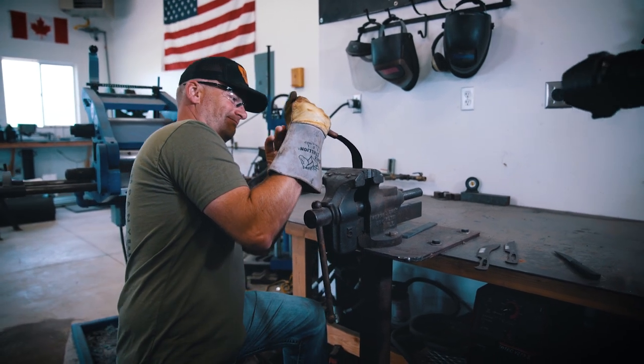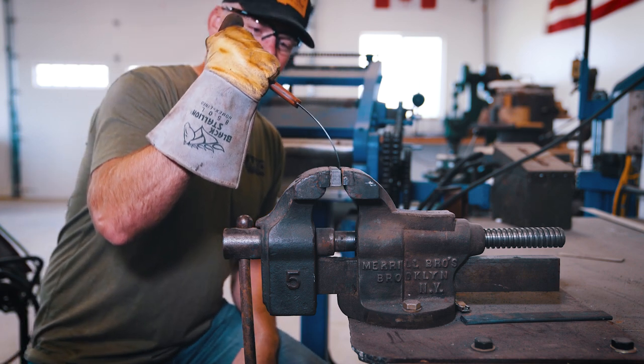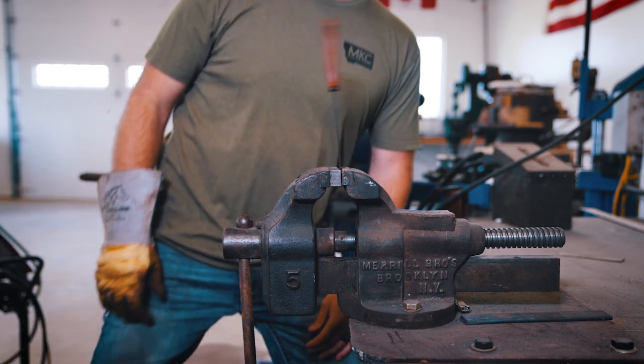It's also a test of how you grind the edge — edge geometry. Edge geometry is key to a blade cutting well. You can heat treat the steel well, but if you do a terrible job on your blade grind it'll be hard to resharpen and hard to cut through a free-swinging rope. After that, you have to bend the blade 90 degrees in a vise — one third of the blade clamped, usually about three inches. A really well heat-treated blade will actually bend 90 degrees and come back almost straight.